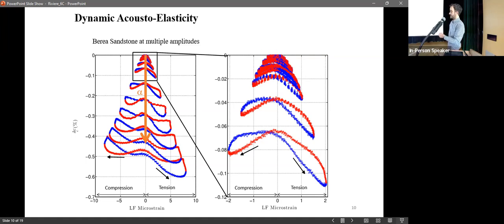Then the next observation is that for some of the signatures, we see a slope. During the tension phase, velocity is slightly lower, so we are kind of opening all the cracks or all the grain junctions. Then during the compression phase, we are increasing the velocity. But especially for that particular sample at intermediate amplitudes, we see this strong curvature. I always use this example because we get remarkable signatures for that sample.